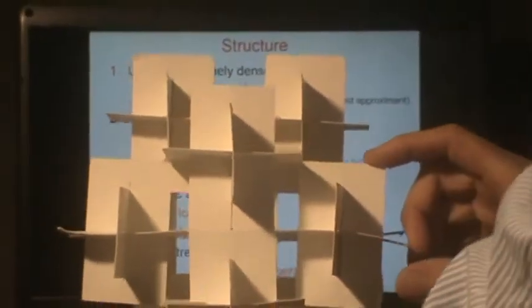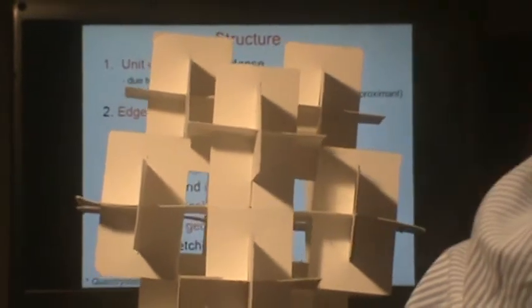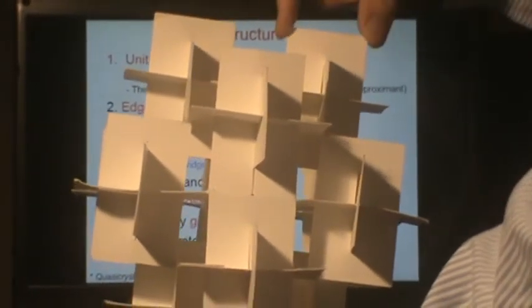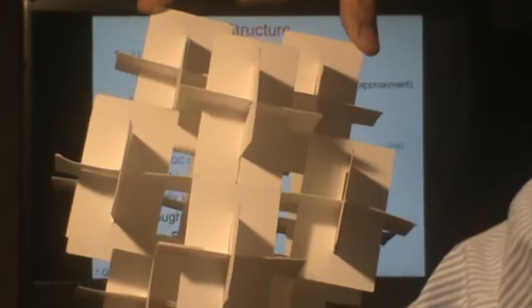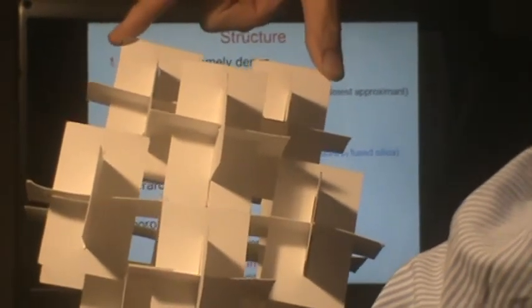Let's work out what is the width of the cluster. 1 over tau plus 1 equals tau. Tau plus 1 equals tau squared. So the stretching factor is 1 to tau squared. And for the supercluster, tau to the 4th. And for the supercluster order 2, tau to the 6th. You've got the idea, haven't you? This is a logarithmically periodic solid with a logarithmic period, tau squared.